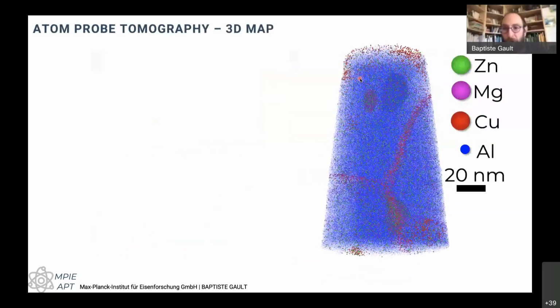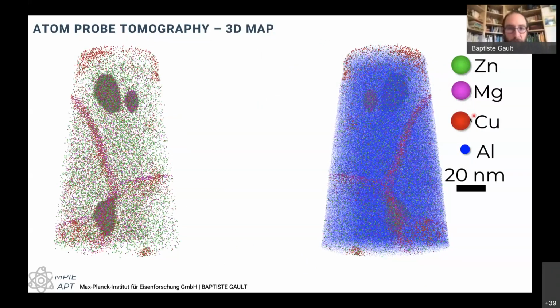But still, that's a typical atom probe data set. This is for nanocrystalline aluminum. You can see it's all in 3 dimensions, and here I have different species. It's a 7000 series, so I have some zinc and magnesium and copper. I have multiple grains. It's nanocrystalline. It was all deformed, so I can see some precipitates inside one of these grains. I can see some solutes segregated to a boundary and to another boundary, and a precipitate sitting at one of the boundaries. These are 2 mirror images, and I can select where's the aluminium, where's the copper, where's the magnesium, where's the zinc. And this is really the information that we get from the atom probe.